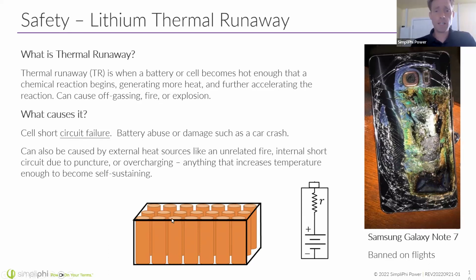That can result in individual cells that are damaged getting very hot. If they develop too much pressure, they can off gas, and that means to release the electrolyte. It's like an organic solvent that allows lithium to move. If that electrolyte releases, it can catch on fire. And if that cell gets hot enough, maybe you have the middle cell catch on fire, it can heat up the cells around it. They can in turn off gas and heat up the cells around them. And that is known as thermal runaway. It's a chain reaction in which one cell heats the next cell, which off gases, which catches fire, which heats the next cell.